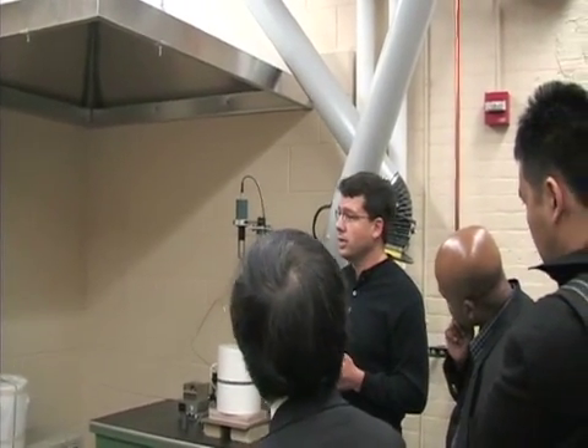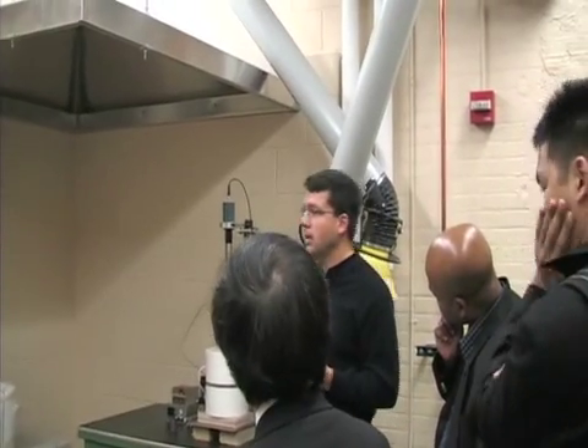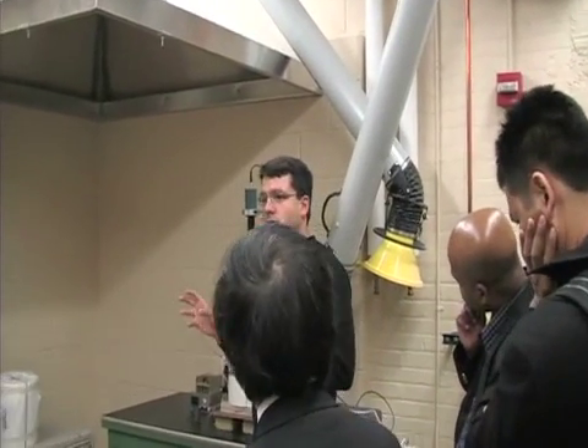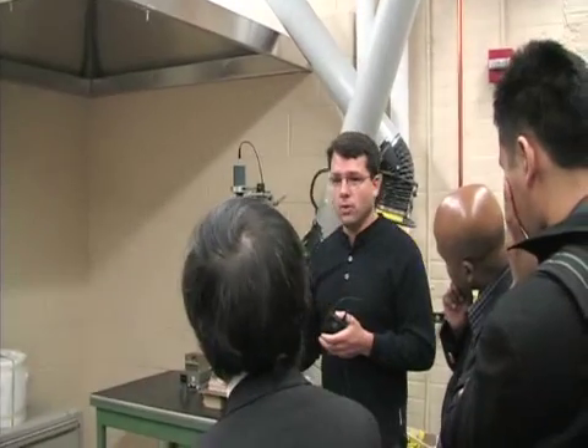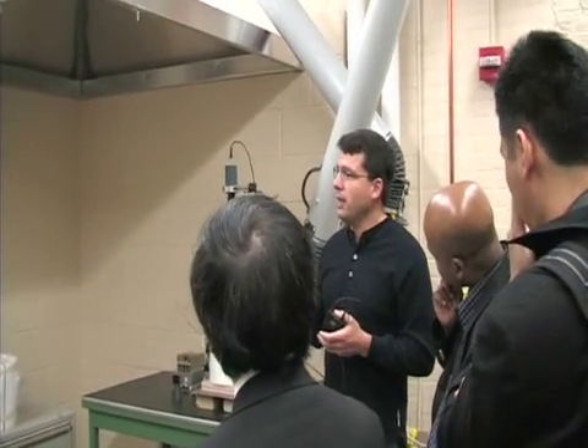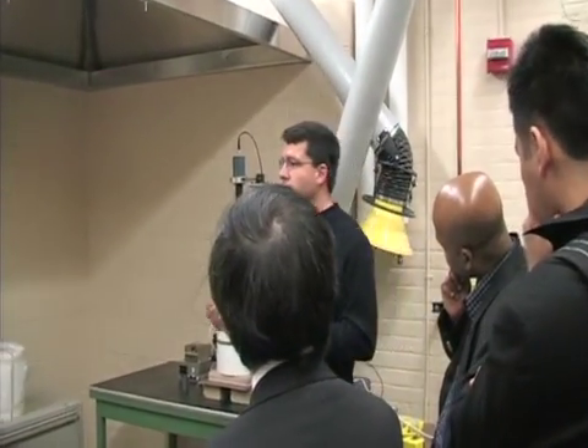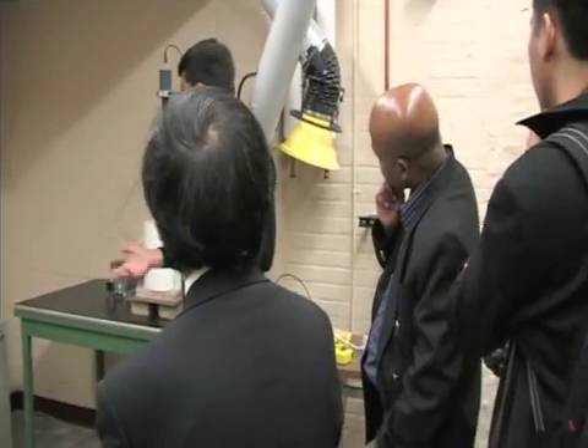The ultrasonic energy creates cavitation events in the melt. These break up the clusters. It also creates a streaming, or sort of a bulk flow, of the material, and that then serves to distribute these now broken up nanoparticles into the melt. And then we can cast it.